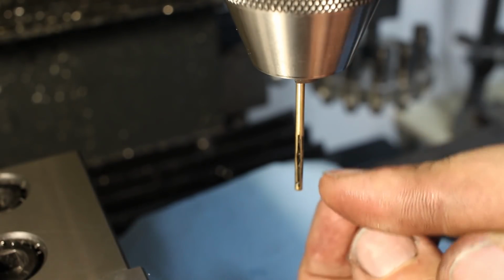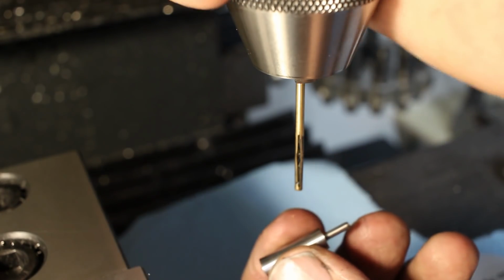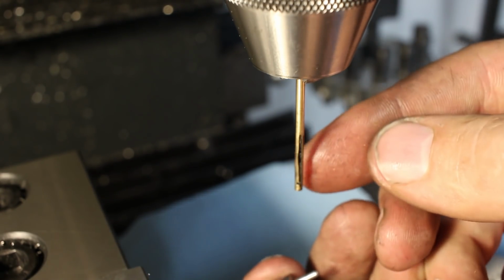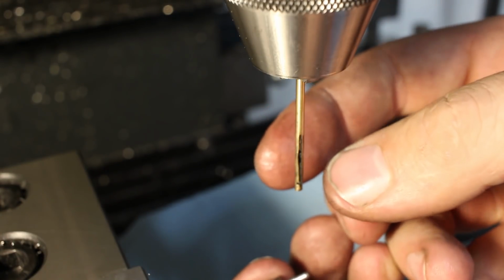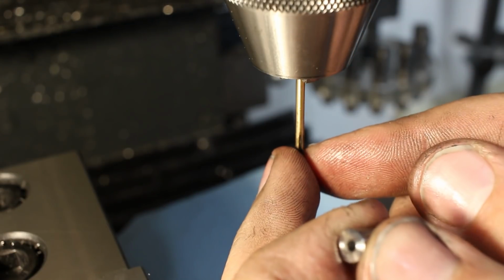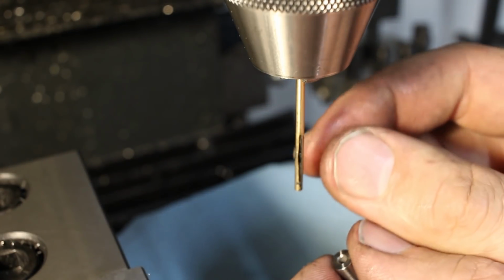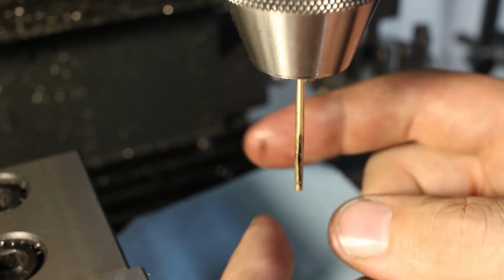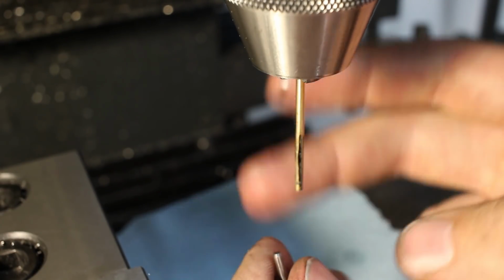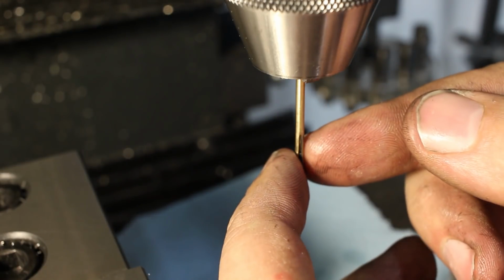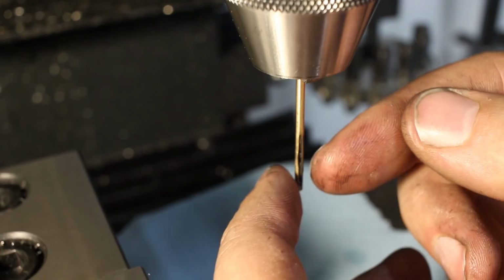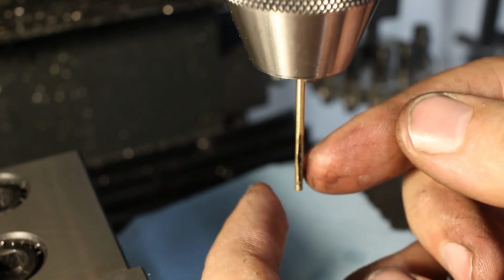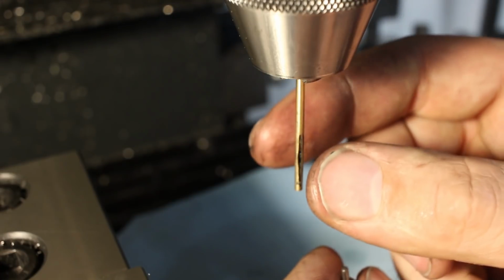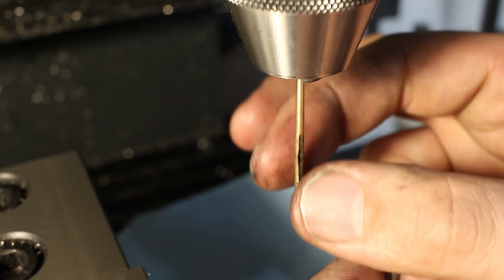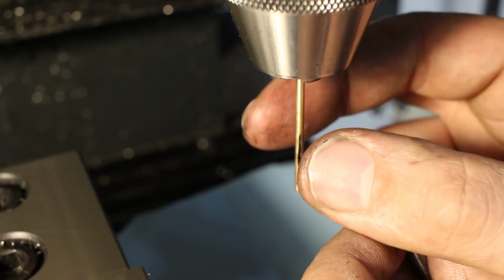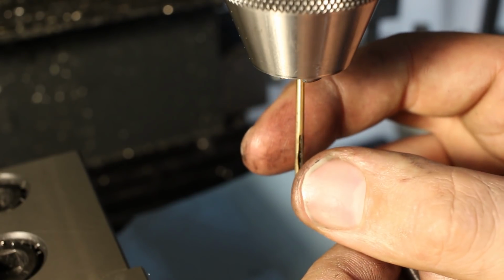And you might have noticed that I didn't have to expand the lap so far. I expanded it once a little bit over 2 millimeters. And this design allows for some spring back. So if you push it over a bore, it almost works like a flex hone that you use for engine refurb, hydraulic refurb, stuff like that. This kind of follows the shape of the bore a little bit, but when you pay attention to how the part drags on the lap, you can very precisely and very accurately control the shape of the bore.